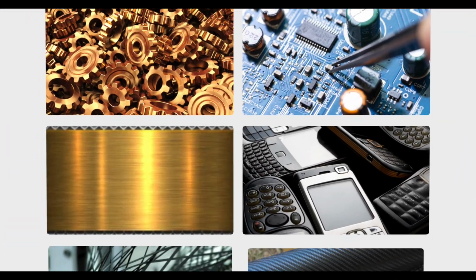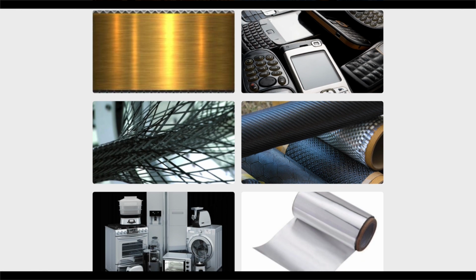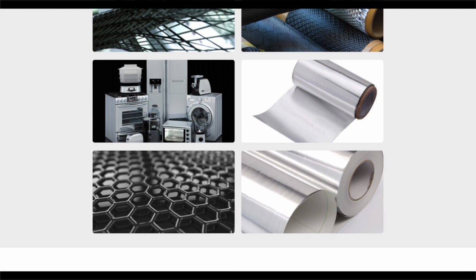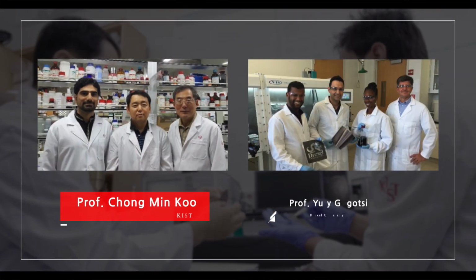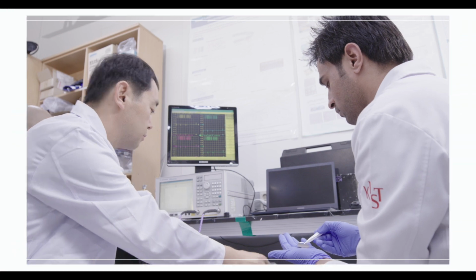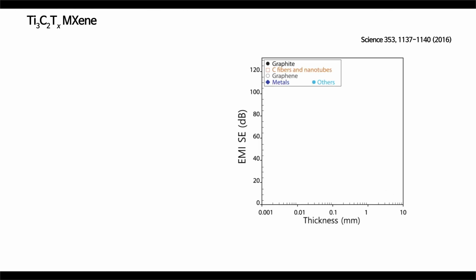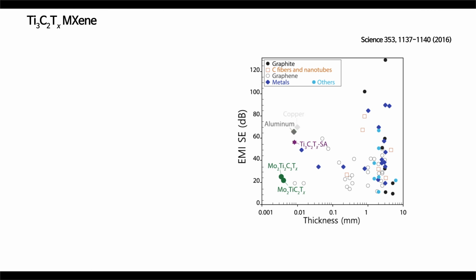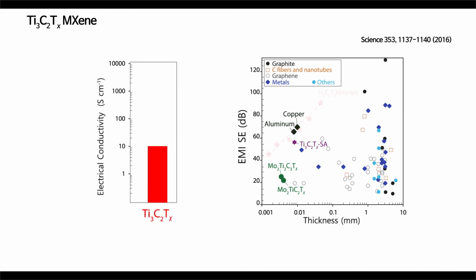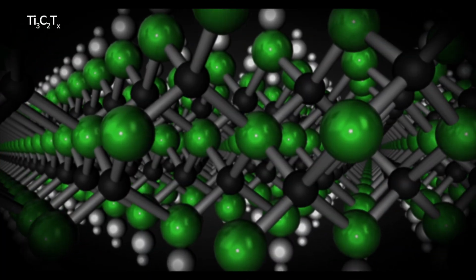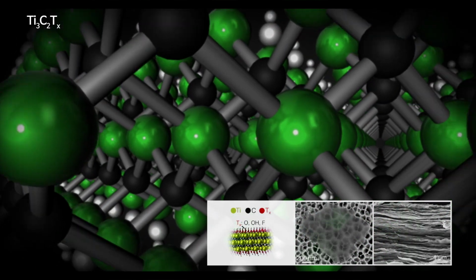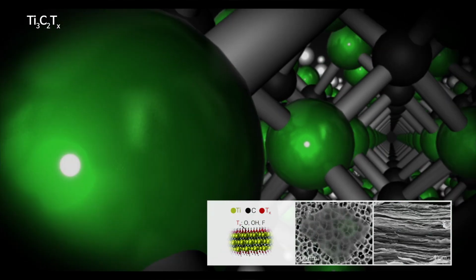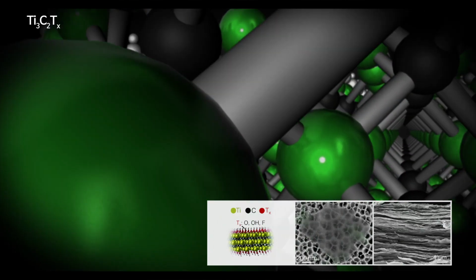However, the most commonly used conducting and non-magnetic shielding materials, such as metals and carbon-based nanomaterials, hardly meet these requirements. In 2016, Professor Chongmin Koo in KIST and Professor Yury Gogotsi in Drexel University reported in Science that Ti3C2 MXene and its polymeric composites showed an outstanding EMI shielding effectiveness of 92 decibels at a very thin thickness of 45 micrometers in X-band frequency range, indicating exceptional promise for lightweight EMI shielding applications. This shielding performance was mainly due to the high electrical conductivity of around 4,500 Siemens per centimeter, abundant surface terminations, and the laminate architecture of Ti3C2 MXene films.